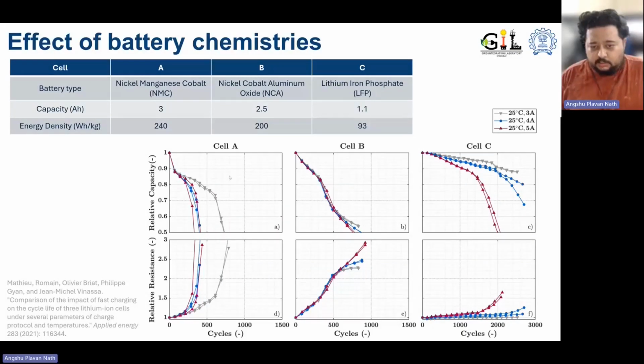So if you see here in the graph, on the top we have the capacity fade, how the capacity fades for cell A, cell B, cell C at a constant temperature of 25 degrees Celsius and for different charging rates: 3, 4, 5 amperes.